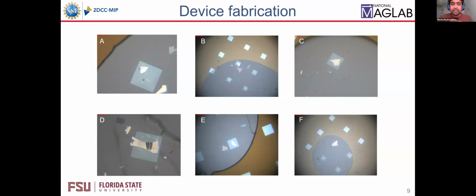Unfortunately, most of the time when I was trying to wash off this polymer, my sample would be dislocated from the grid position. The silicon nitride membrane is not very adhesive to the flake. So when I was washing with chloroform, the flake would just move from its position. I think I made 6 or 7 stacks, but only 1 or 2 survived till the end.